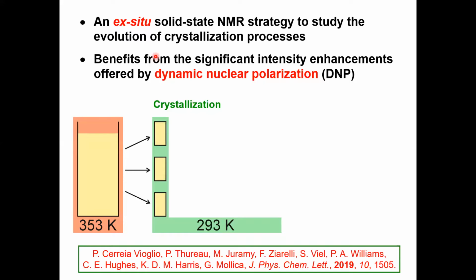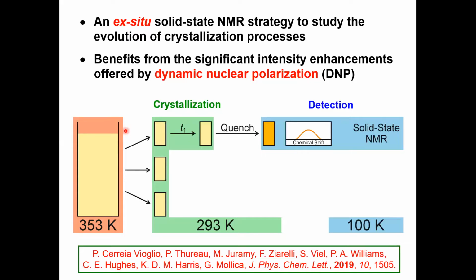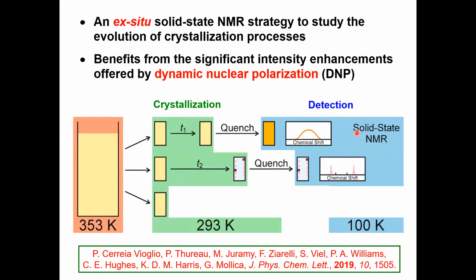So the basis of the idea is the following. Again, we start off with the crystallization solution at high temperature. We subdivide that into several different NMR rotors, and we allow the crystallization to evolve in parallel in each of these NMR rotors. Then after a particular period of time, T1 in this case, we quench that crystallization solution in the NMR spectrometer and measure the solid-state DNP NMR spectrum. We leave the next one for a slightly longer time, quench it again, and study the NMR spectrum, and so on. The point is, after you quench the crystallization system, there's no further evolution of the crystallization.